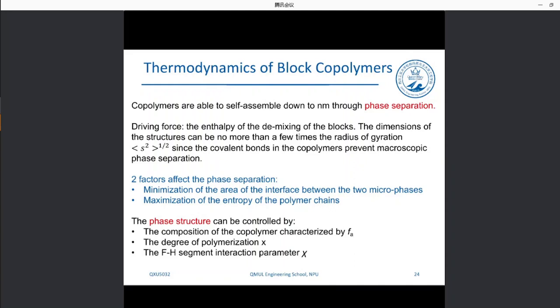a way that is a bit similar to polymer blends. However, the structures that are created are much finer, much smaller, and they have strong bonding, a good interface between the two phases. Okay, so that is the main difference between polymer blends and copolymers. However, as we said a few times now, in block copolymers, we have this extra constraint that the constituent blocks, the two phases, are connected through covalent bonds, okay? And because these materials are connected through covalent bonds, these prevent the macroscopic phase separation, okay? The covalent bonds in copolymers prevent phase separation, okay?